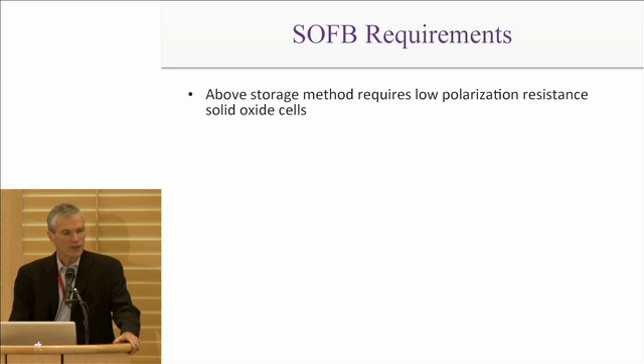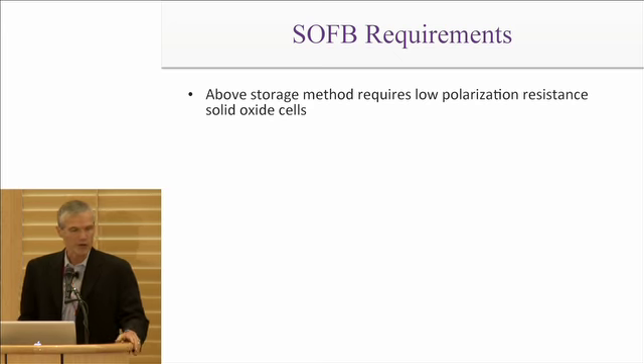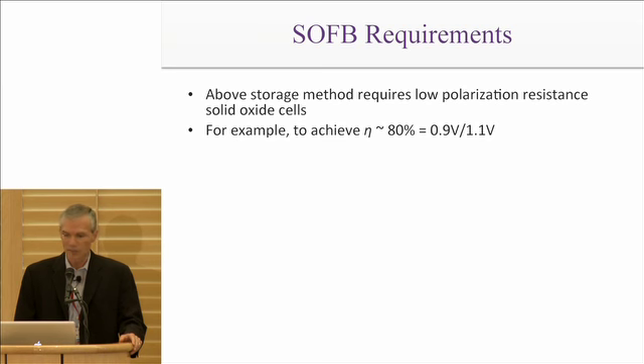Okay, so this gives us actually a couple of operating modes that we can operate this device in, and based on these considerations, we came up with some requirements on these devices. Okay, so first off, we need to have a device that's going to give us a very low polarization resistance in order to allow us to operate under these conditions. So basically what I just said was that we want to have a high efficiency like 80%. For example, we might want to operate in fuel cell mode at 0.9 volts and electrolysis mode at 1.1 volts with a 1 volt Nernst potential.